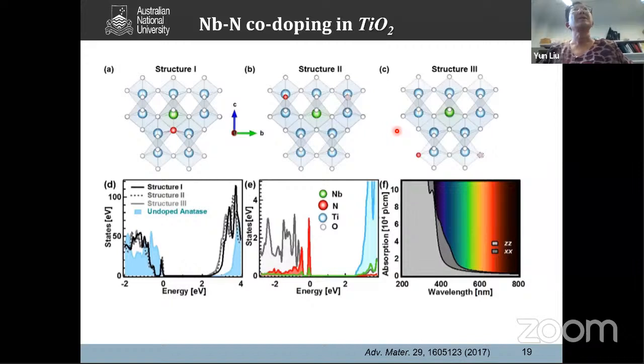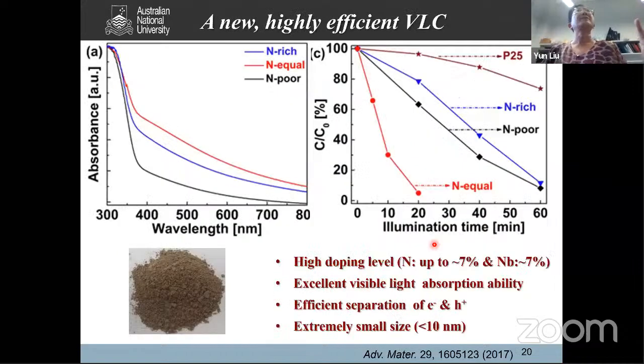This kind of environment also allows you to attract more nitrogen, which gives you much stronger visible light absorption. As a result, you can see here a comparison of 3 samples: one has nitrogen concentration higher than niobium, another has nitrogen equivalent to niobium, and another has nitrogen less than niobium. We call them nitrogen rich, nitrogen equal, and nitrogen poor. As you can see, only when the niobium and the nitrogen form the pair do they give you much better absorption and much better photocatalysis effects. Okay, so that is how we can use this defect strategy to modify the materials and the photocatalysis.